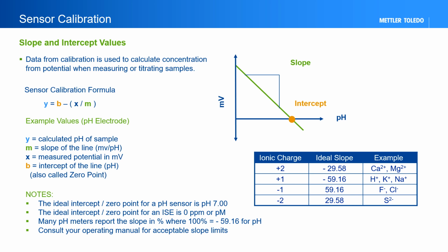Ideal slopes for a sensor depend on the ion being measured. Most ideal slopes are displayed in the table. The ideal zero point for a pH sensor is pH 7, and for sensors measuring in parts per million or PPM values, it is 0 parts per million or 0 PPM. Many meters reference the slope in terms of percentage. This is simply the percent to the ideal slope. Consult your operating manual for suggested slope and 0-point limits. Typical slope limits are 90 to 110% or the millivolt value equivalent.